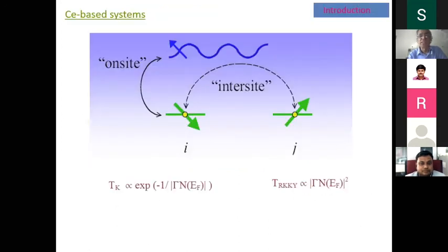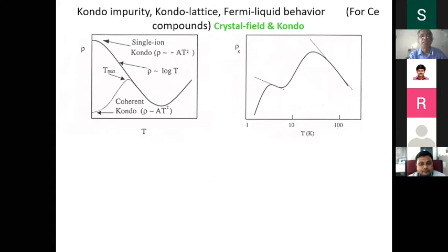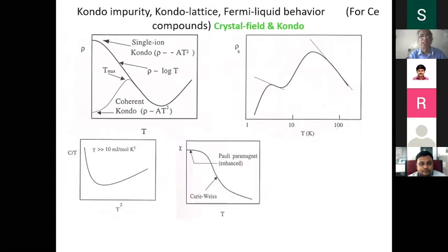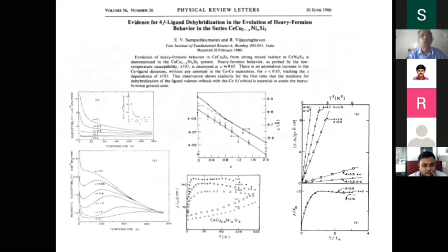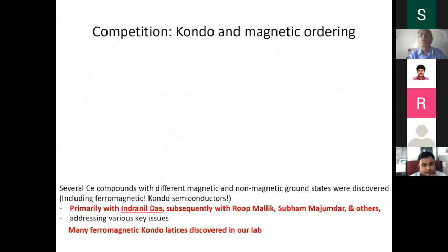Now, as I already mentioned, the on-site Kondo interaction, which goes exponentially with the local interaction, competes with the intersite interaction, which is RKKY. If you collect a large number of cerium ions or europium ions, they compete, and this competition between the two can give rise to a lot of problems. So then you have competition between the Kondo effect and magnetic ordering.